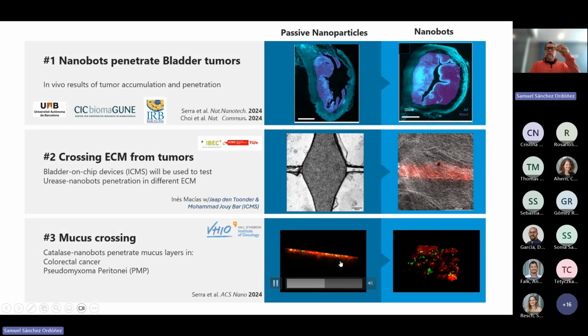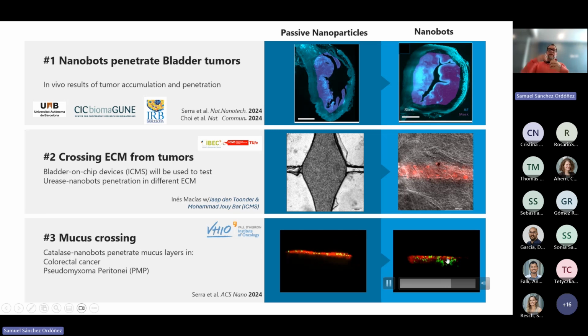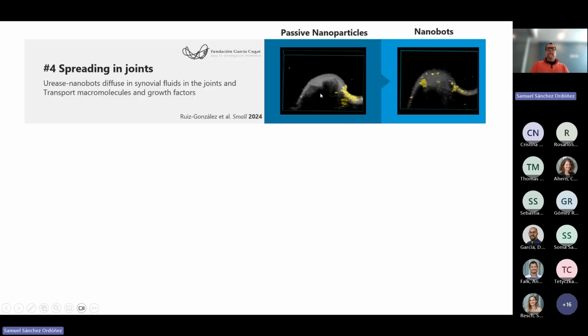So the passive nanoparticles will get stuck, and they get very sticky to the mucus layer, they don't penetrate, but this catalase generates oxygen bubbles. They can propel and push and make gaps and voids and let the nanoparticles with the medicine cross the mucus. And we are doing these experiments for pseudomyxoma peritonei, a very rare disease, and we are having good results in vivo. Then other places where viscosity is very high, and therefore is a biological barrier, are the joints.